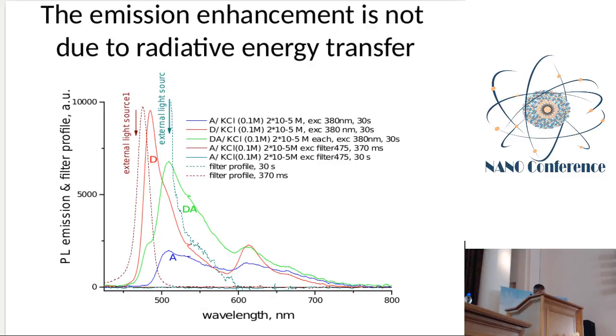You can ask me whether this can be done by radiative energy transfer, but we made a special experiment which rules out this possibility. When we directly illuminate a solution of the acceptor J aggregates with the wavelengths which are the same as the wavelengths of the donor emission, we did not observe any enhancement of the acceptor photoluminescence. So the emission is very low here.